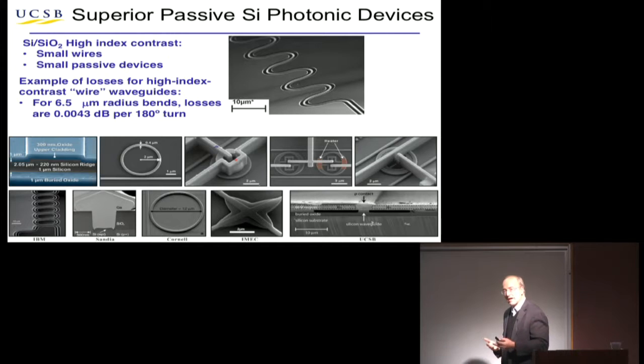So a couple of comments again for people who aren't in the field. Why use silicon? If you look at indium phosphide and an InGaAsP process, the waveguide has an index of say 3.5. The cladding has an index of 3.3. So it's 0.2 index difference, and that's pretty minimal. So you can't make sharp bends, but in silicon, index 3.5 to 1.5, you can make very sharp bends, and the bend loss is extraordinarily small, right? So even for a 6 micron radius bend, a few thousandths of a dB per turn. So you can make arrays of rings, and there's lots of interesting filters and things that one can do, and so it works really well.